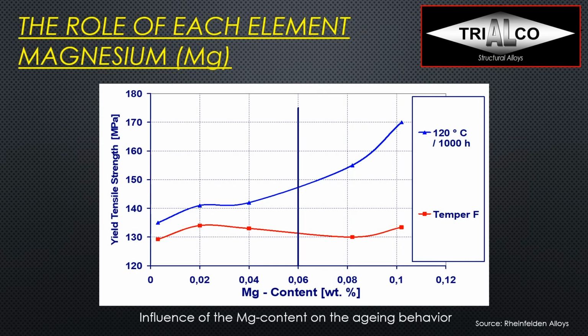Now, if we look at the aging response, you can see this very nicely here, that with increasing magnesium content, if the magnesium content is low in F-temper, the aging response isn't much. We can see here increasing magnesium does a little bit, and we're just looking at very low contents up to 0.1%. But see that at 120 C for 1000 hours, so over time, it would age naturally, or if we go to a higher temperature, we can artificially age, and we can see that really as soon as I surpass, here we say 0.06%, I would say approximately 0.05%, the yield strength goes up very quickly. So that shows us the heat treatment response coming from the magnesium silicide hardening.